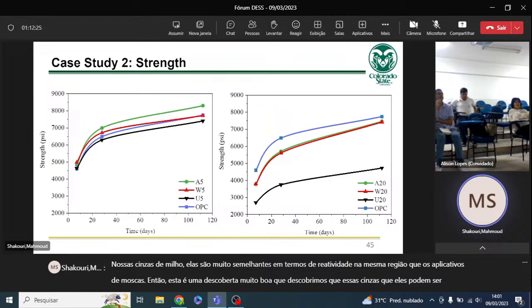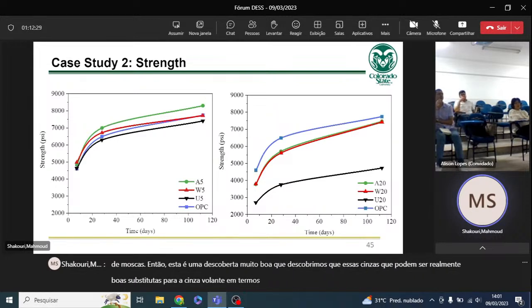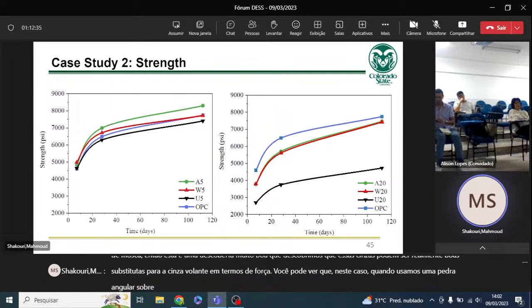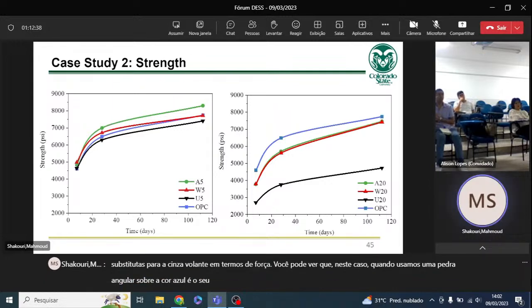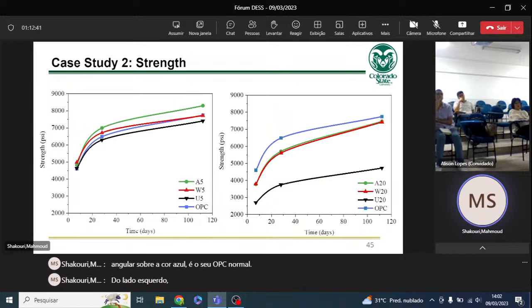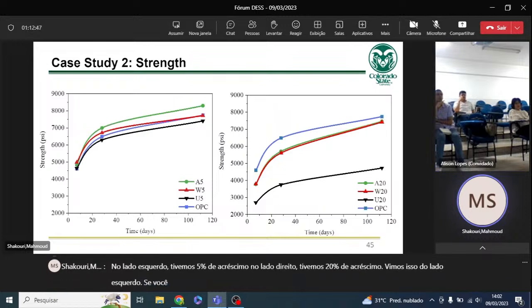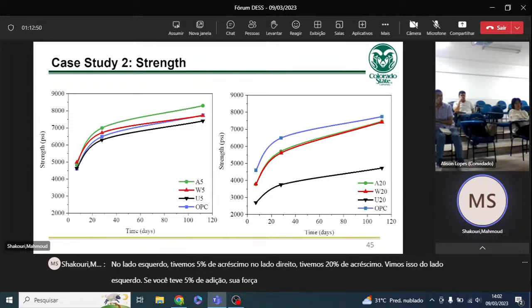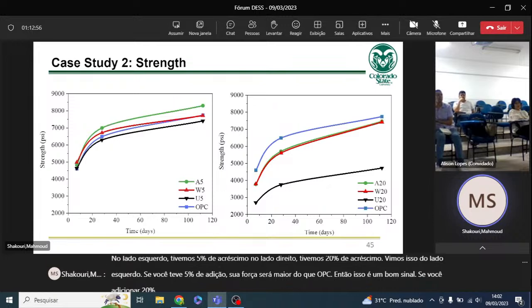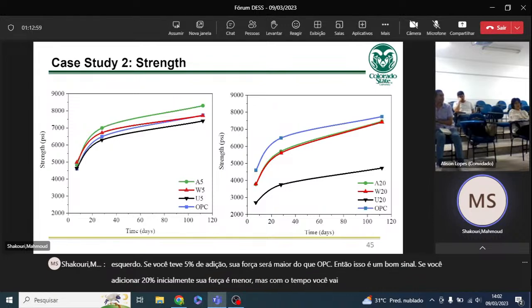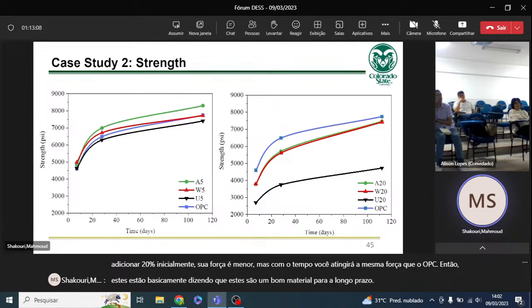replacement for fly ash. In terms of strength, you can see that in this case, when we used corn stover, the blue color is your normal OPC. On the left side, we had 5% addition. On the right side, we had 20% addition. We saw that on the left side, if you had 5% addition, your strength is higher than OPC. So that's a good sign. If you add 20%, initially your strength is lower, but over time you will reach the same strength as OPC. So these are basically telling you that these are good materials for long-term performance.